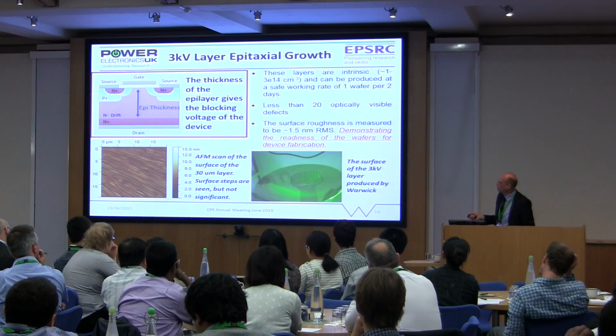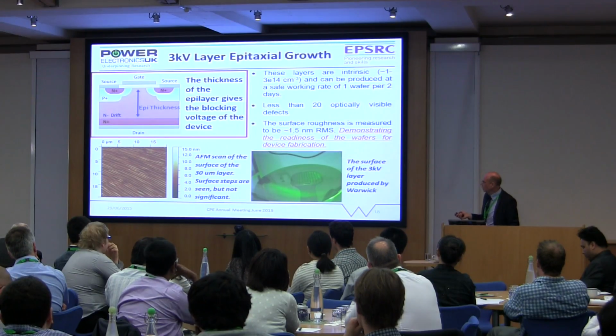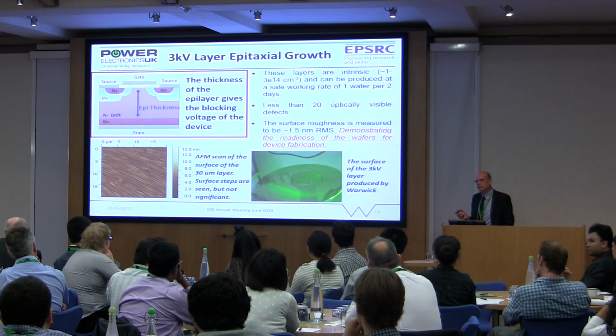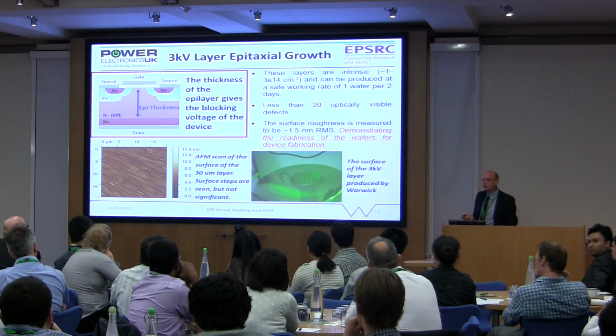And it's also difficult to grow them quickly, and it's difficult to grow them with good quality. So what we've been focusing on is trying to grow these thick layers quickly, and we can grow 100 microns in about an hour or two, which is very fast indeed, and the quality is excellent. We've bought an epi reactor for this. A special piece of equipment we bought through linkage with this project, and it's the only one in the UK that can be used to grow this silicon carbide material.